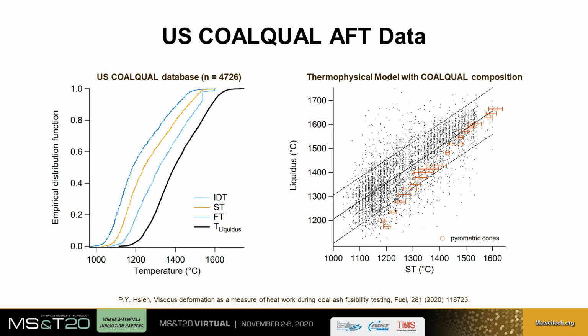This is because these critical temperatures measure heat work, or the combined effect of time and temperature, in the same manner as pyrometric cones. Contrary to expectation, AFT critical temperatures are not strongly correlated with the solidus temperature, but are correlated with the liquidus temperature. So what is going on here?